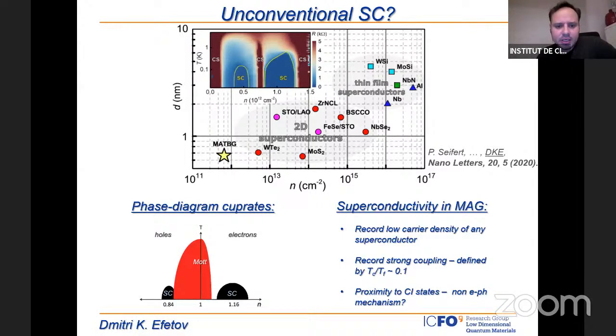The other thing that was immediately intriguing is that the carrier density from which this superconductor is formed is somehow record low. Here we made a graph contrasting the carrier densities for typical superconductors, and as you can see, magic angle graphene is by far the thinnest superconductor in existence, but it also has a carrier density which is orders and orders of magnitude lower than in conventional superconductors, and also much lower than in high temperature superconductors.